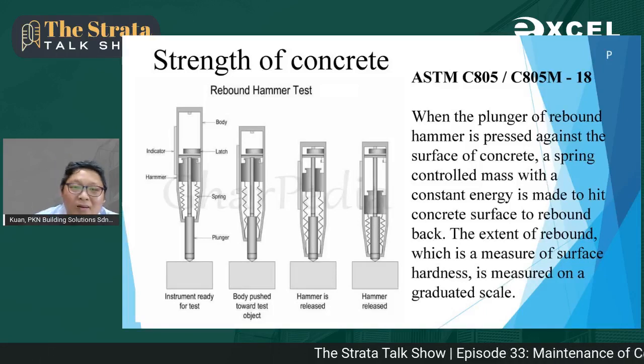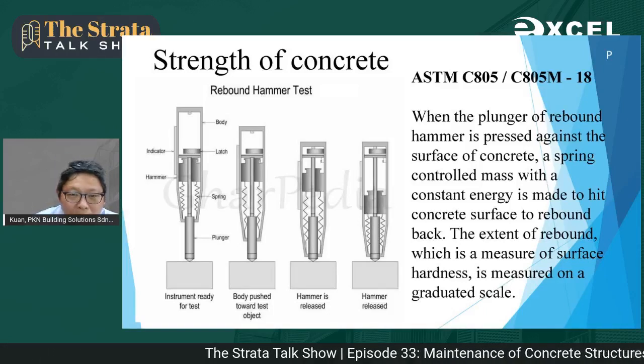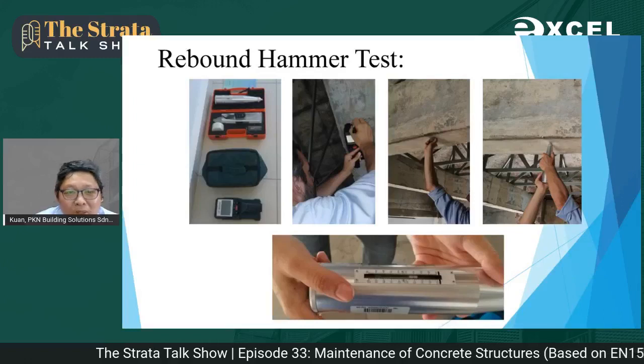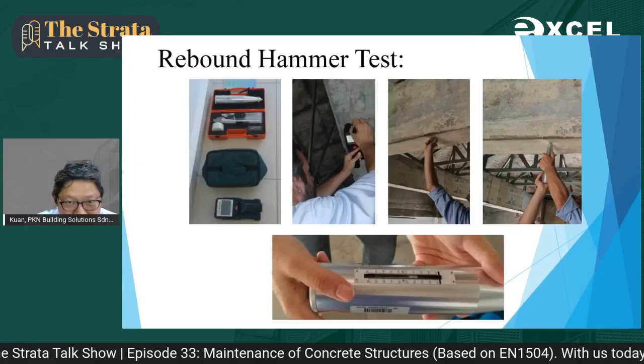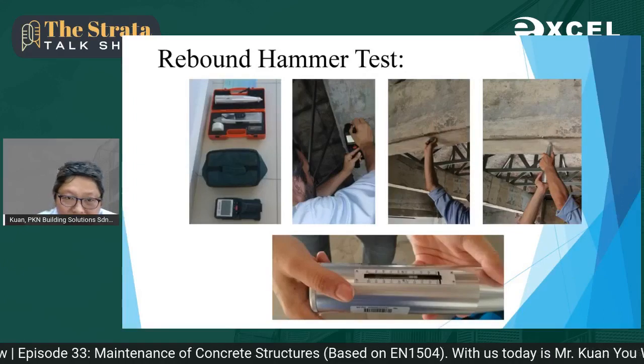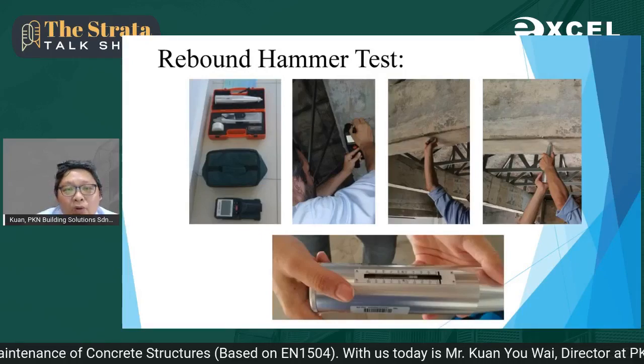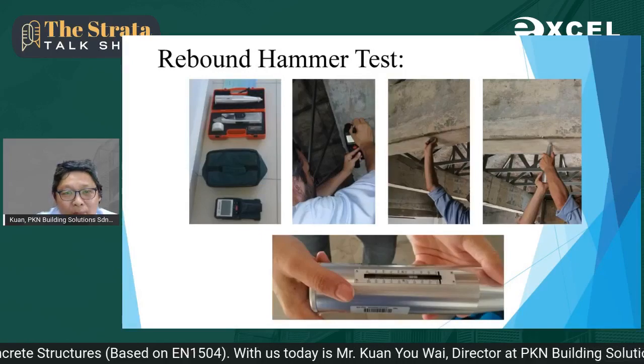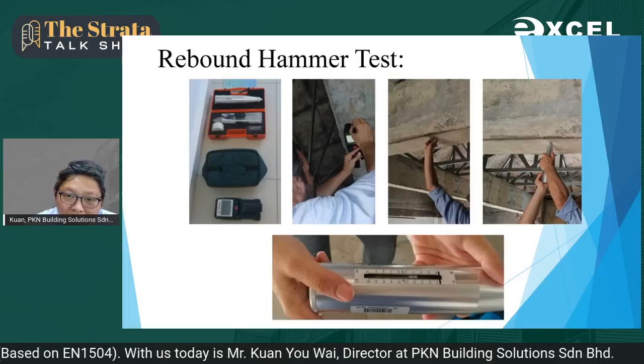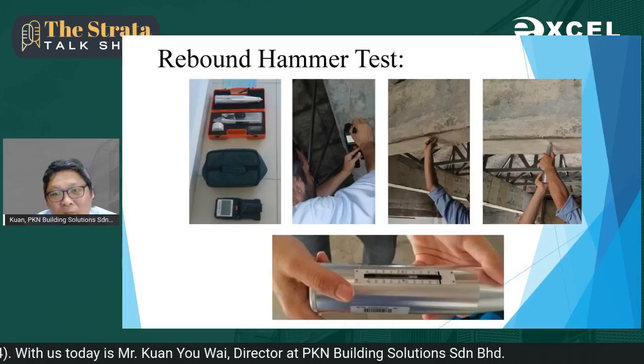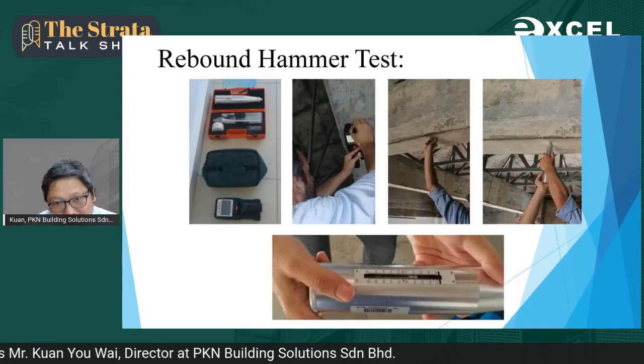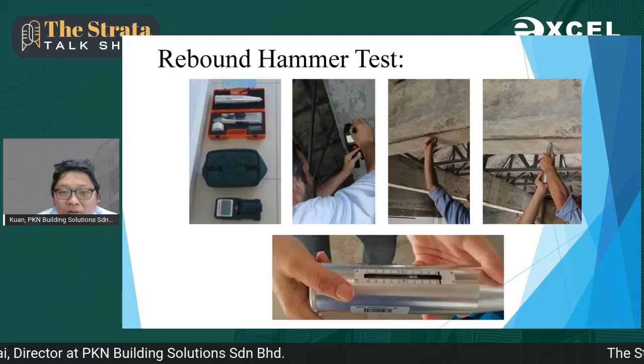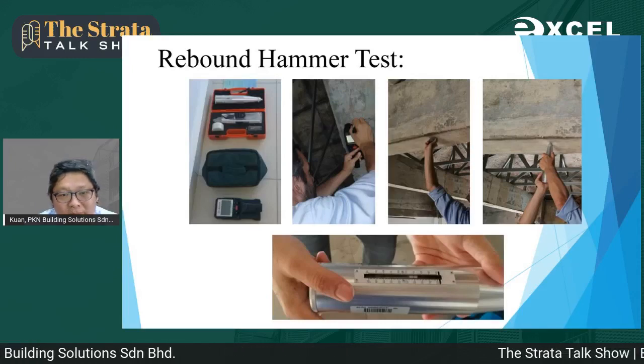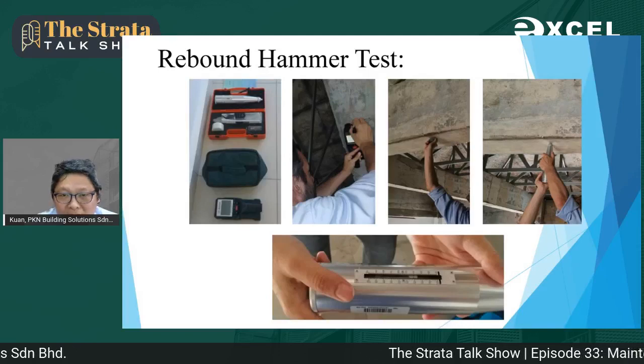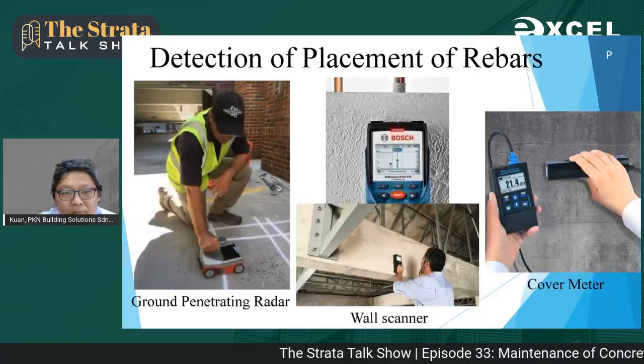So the more correct way is to use a scanner to identify where the reinforcement steel bar is, and we only use the rebound hammer to measure on areas without reinforcement steel bar, or in between two reinforcement steel bars, so that we can get a more accurate reading. Okay, so this is how we do it at site.